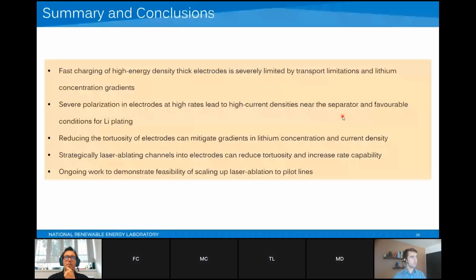scale up. So in summary, fast charging of high energy density thick electrodes is severely limited by transport limitations and lithium concentration gradients. We get severe polarization in electrodes at high rates due to high current densities near a separator, favorable conditions for lithium plating.